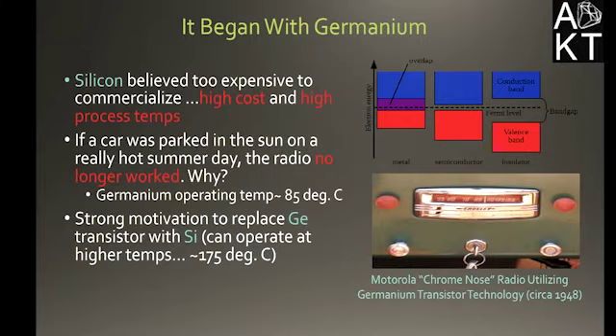But when incorporating this germanium technology in products like a germanium transistor radio, it was found that if your car was parked outside on a very hot day, and you came back to your car and turned on the radio, it no longer worked. Now, why is that? Well, as it turns out, germanium is not very heat efficient. Actually, it operates at about 85 degrees C optimally. And above that, it reverts to intrinsic use.